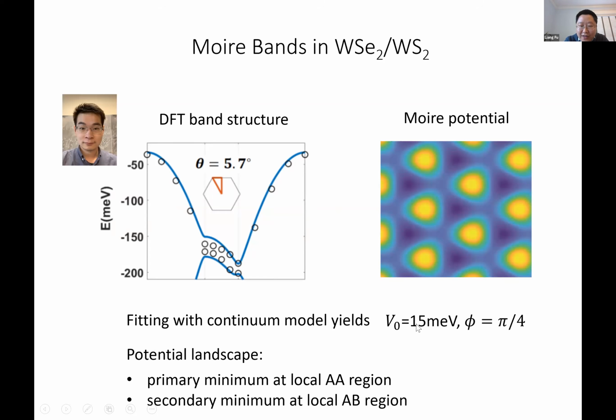So the strength is 15 milli-electron volt. The parameter phi is about 45 degrees. And when we plot this Moiré potential, you notice that this potential has a primary minimum. Here I'm thinking of this potential for the holes. So the first band corresponds to states dominated by holes that are localized in the minimum